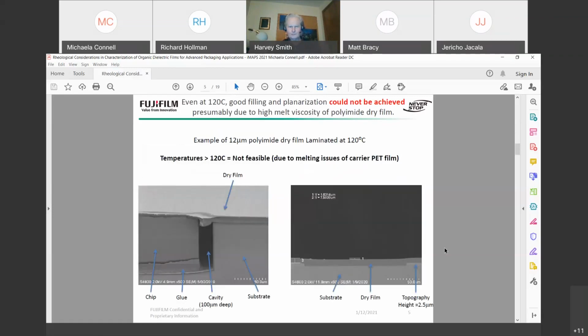So here we have an example of a typical polyimide dry film laminated at 120 degrees Celsius. As you can see, even at 120 degrees Celsius, good filling and planarization could not be achieved, presumably due to high melt viscosity of polyimide dry film. On the left, we have an embedded chip with a 100 micron deep and 25 to 30 micron wide cavity between the chip and the substrate. And with 12 micron dry film, even when laminated at 120 degrees Celsius, we were unable to create enough flow to even achieve 10% of filling.